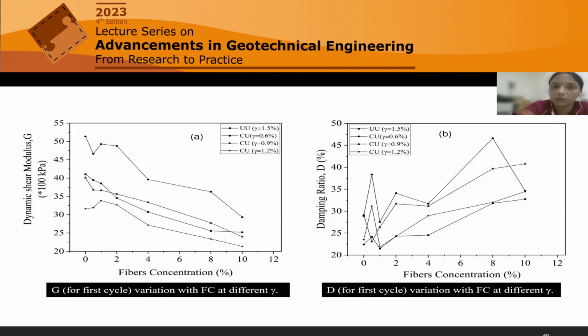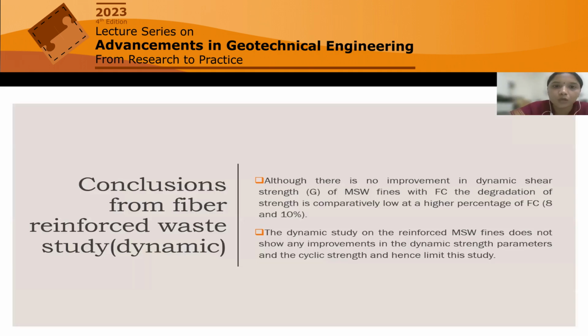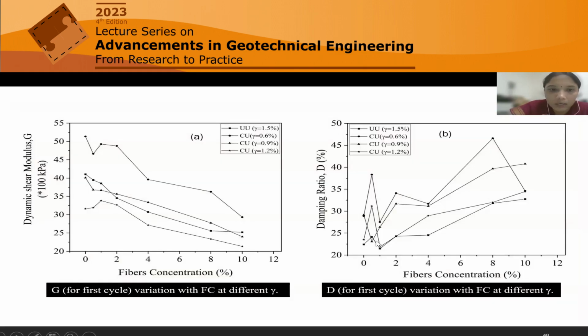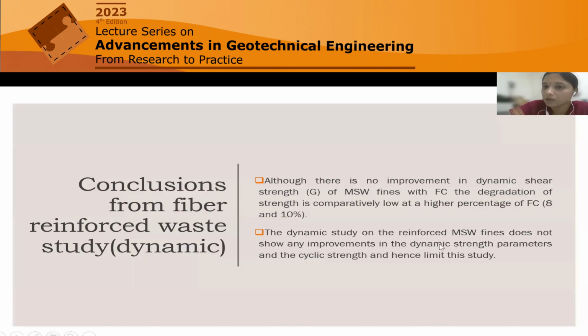But with this particular waste fiber, it is not giving us any improvement in dynamic parameters. So the conclusion from this fiber reinforced waste is that no improvement in dynamic shear modulus of this MSW fine with fiber content has been noticed. And if you compare 8% and 10%, the rate of degradation is relatively low, but still it is decreasing. The dynamic study on reinforced MSW fine doesn't show any improvement in dynamic strength parameters and the cyclic strength, hence limiting this particular study.